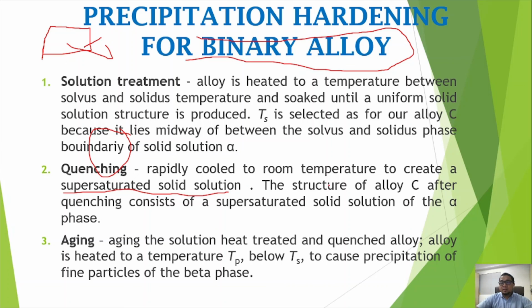So the structure of alloy C after quenching consists of a supersaturated solid solution of alpha phase. Then the third one is aging. Aging ni penuaan, sama juga macam kita pun menua. So aging, the solution heat treated and quench alloy. Alloy is heated to a temperature below Ts to cause precipitation of fine particle of the beta phase.